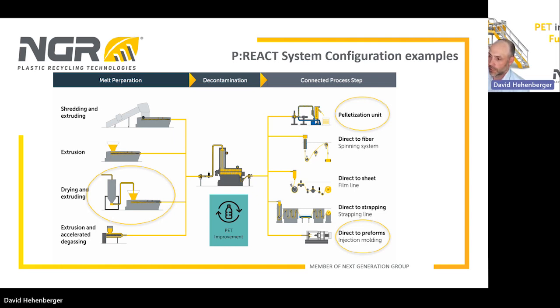In the LSP reactor, we decontaminate the material, we lift the viscosity, we build up enough pressure, and we take care that the throughput is very constant. And this all is done within about 30 minutes in the reactor. And after that, you are very flexible because of the constant melt quality. You can go into pelletizing or several inline applications like fiber, sheet, strapping, or finally, you can also use the LSP reactor directly in front of an injection molding machine in order to reduce energy consumption, save investment and material logistics.